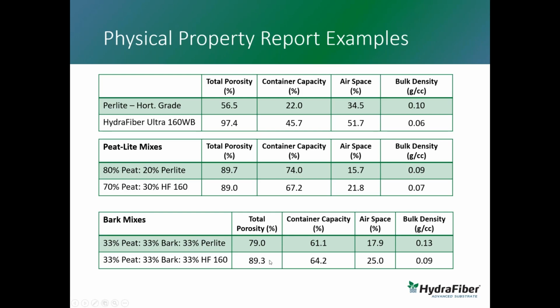We see here that we increase total porosity significantly in the mix with Hydra Fiber. We see here that we are actually able to increase the water holding capacity. So 3 percentage points, that may not seem like a lot, but that's a decent amount of water holding capacity. But look at this, the airspace, we're significantly increasing the airspace.